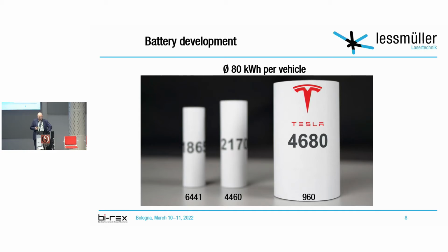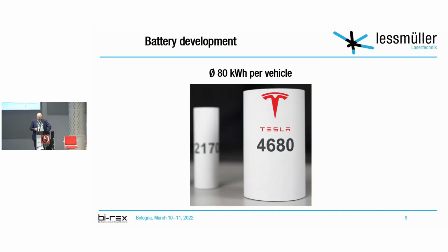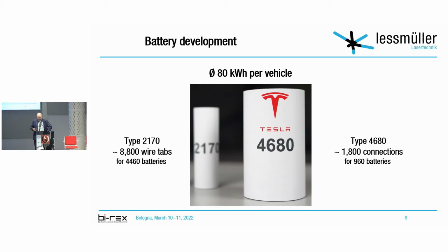And the good news is, I'm a laser guy as well, a lot of the applications will be done by laser. And you have a minimum of 2 times the connections as the number of batteries, because you have 2 poles, so you need at least 2 welds. But in reality, you need more. So this means for the latest type, we need about 2,000 connections per car. And all of those should be good ones.